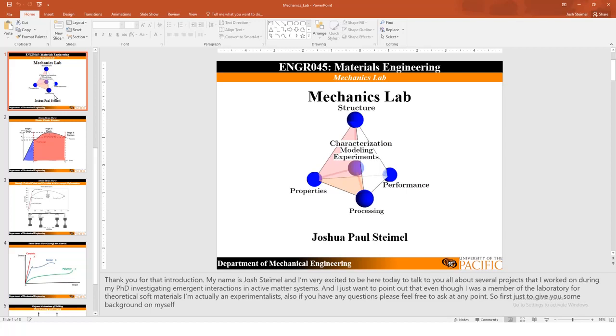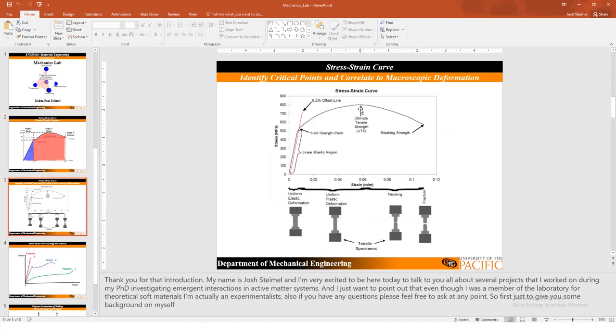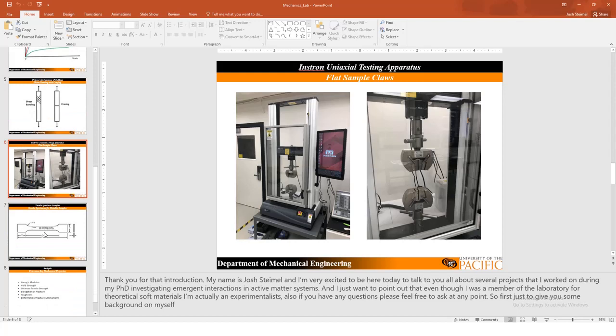But instead, we are going to analyze the data and figure out how to plot stress-strain curves. We've talked about and seen this curve in previous lectures. Again, this is where essentially your necking point will occur. What we would have done in class is use this Instron machine. You basically put your sample in between here. We have dog bone shape flat samples, so we have grips that are made for flat versus cylindrical samples. We were going to pull this at a constant strain rate of 10 millimeters per minute and basically stretch our sample until it fractures and measure the stress-strain curves. That's what we would have done if we were in person lab. You can see this nice blast shield to make sure that if it breaks, it doesn't pop back out at you. So that would have been a nice experiment.